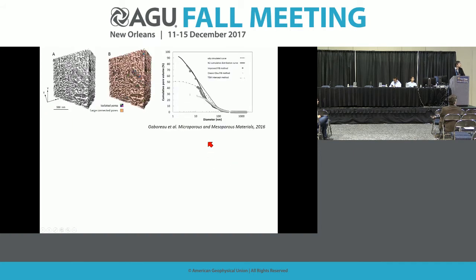So one type of additional constraint could come from the effect of the microstructure. The microstructure of clay samples can now be measured and characterized with several types of techniques, bulk techniques like gas adsorption isotherms. Here you have the cumulative pore volume as a function of pore diameters. The line is this gas adsorption experiment. But you can also use imaging techniques, for example focused ion beam SEM, in order to get the distribution, position and size of the pores in 3D images. That's typically what you have with the points here, the dark gray ones, that follow this nitrogen adsorption curve nicely, which gives you confidence in the thresholding technique you used in order to obtain the information.